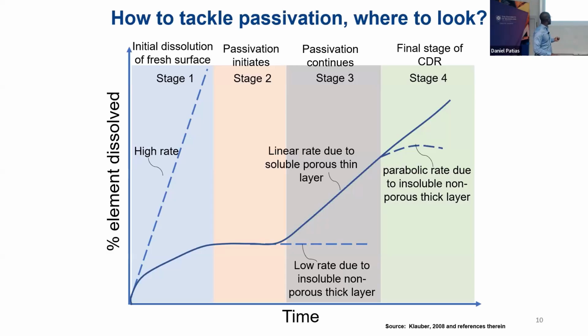So if you plot a graph of percent copper dissolved per time, initially with a fresh surface, you have a much higher rate of copper mobilization. With time, if you form insoluble, non-porous, thick layers, which often cover the reactive surface area, and inside a heap, clog the pores, you then have a decline in your copper.